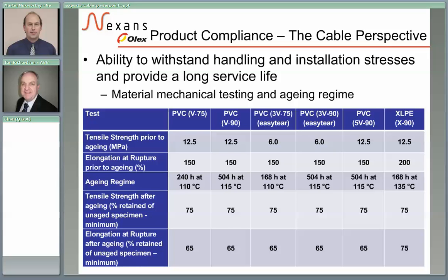The bottom two rows show us the pass criteria after the material is aged, and what they mean is that after the material is aged, the tensile property of the material can be no less than 75% of the original unaged value, and the elongation can be no less than 65% of the original unaged value.